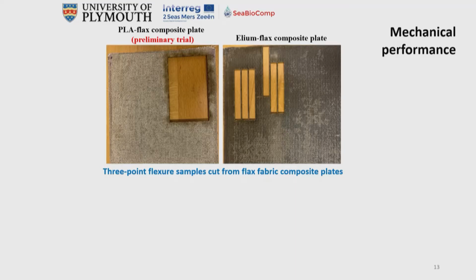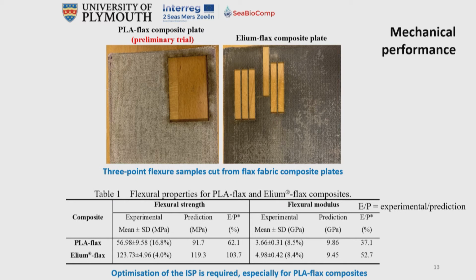We then made some composites with the flax PLA and with the Elium and got these mechanical properties. At this point, I'm desperate to use the pointer and it doesn't work for those people online or those in the room. But the top line is flax PLA, and the experimental strength only comes out at 60%, and the experimental modulus only comes out at 37%. For the Elium acrylic, we're getting sensible strengths as we would predict, but again, the flexural modulus is low. So we need optimization of the in situ polymerization, especially for the flax PLA composites.